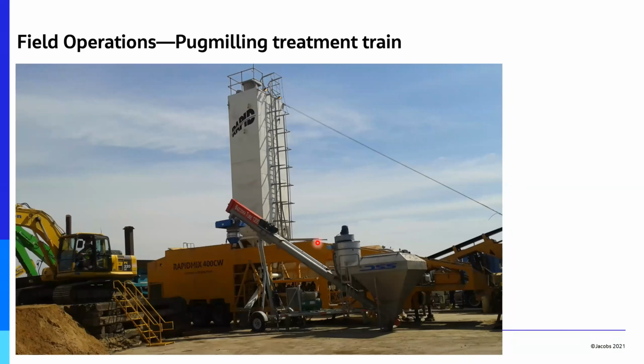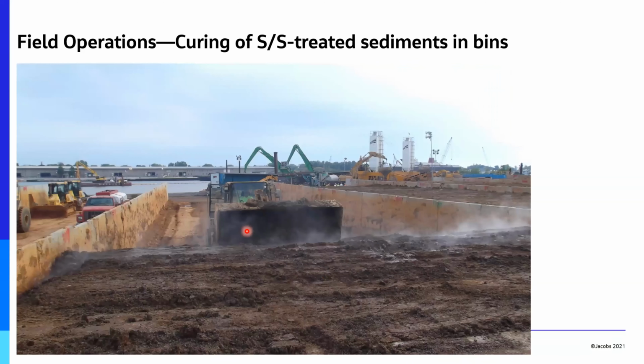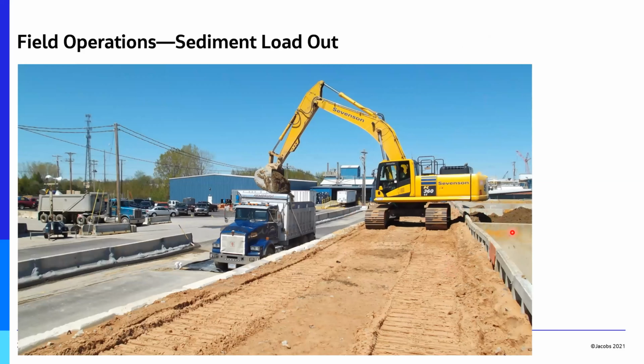This is the device that put in the ferric sulfate, the dry mix. And then here is a loader filling up a bin. This is steaming because the ferric sulfate, in combination with Portland cement, is very exothermic. So it's driving off a lot of moisture at the same time it's immobilizing the arsenic. Now, here's the bin with the impacted material on the right-hand side. The excavator swivels around to the other side and fills up the truck that's going to the landfill. So it fills it here, then it goes through a truck wash system before it goes off-site to the landfill.